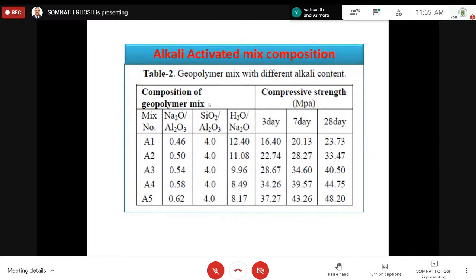I must be sure whether at all a geopolymeric reaction is taking place or not. Long back, when people used to add alkali and sodium silicate to blast furnace slag, they used to call it geopolymer. But then, throughout the world, they said, why are you calling it geopolymer? Why is the polymer term used? Because no polymeric reaction is taking place.